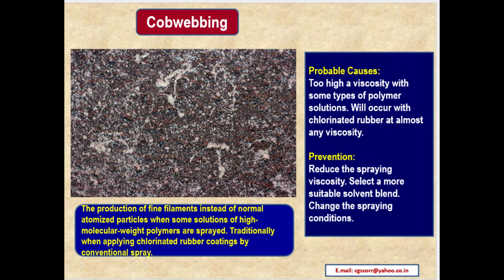The next defect is cobwebbing, which has been described picturesquely on the top left of the slide. The production of filaments instead of normal atomized particles when some solutions of high molecular weight polymers are sprayed. Traditionally, when applying chlorinated rubber coatings by conventional spray. Probable causes: too high a viscosity. With some types of polymer solutions it will occur with chlorinated rubber at almost any viscosity. Prevention: reduce the spraying viscosity, select a more suitable solvent blend, change the spraying conditions.